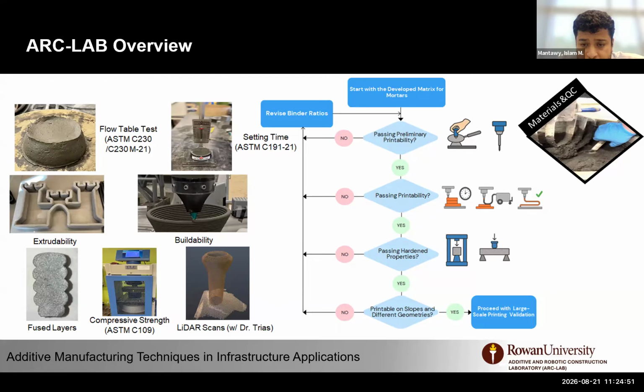After that, we end up with hardened structures that we test for flexure, compression, and others. We also collaborate with a faculty here, Dr. Trias, with LiDAR scanning to capture the geometry of the structure, during and after printing, to compare as-printed versus the CAD model. When we fail in any of those, we go back and adjust our binder. But since 2023, we have different versions of those materials, so we are now in the phase of using those to build structures.